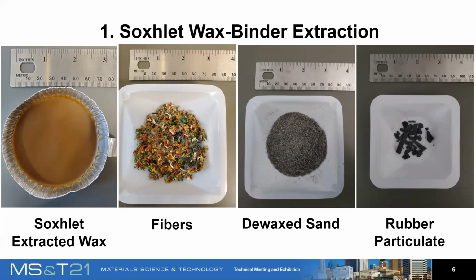As a reference, the fibers usually make up around 10 to 15%. The rubber is less than 5%. The wax binder makes between 4 to 6% and is usually responsible for it holding together. And the rest of the sample, the majority of the sample, consists of the granular mineral sand.